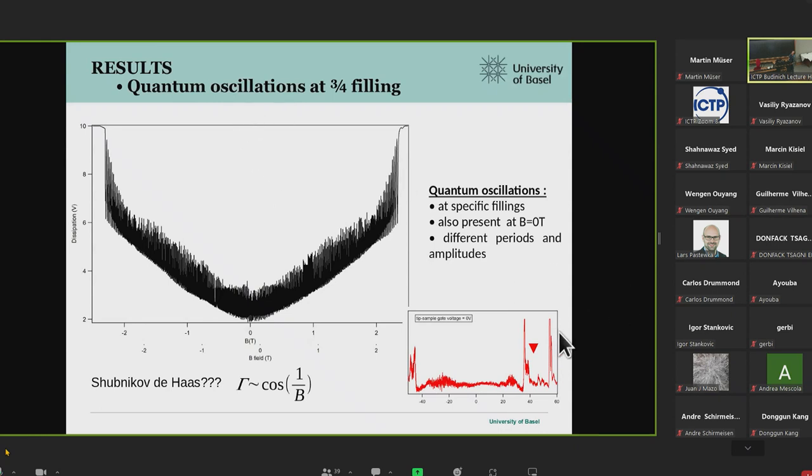Between 3/4 and full filling, we observe something that we called oscillations. So you see dissipation versus magnetic field starts to oscillate, so you have this mustache of oscillations. At the beginning, we were thinking that this could be characteristic Shubnikov-de Haas oscillations, but there are two problems with that. Shubnikov-de Haas would require a metallic Fermi surface, and this is in fact an insulating state, so this Fermi surface cannot be metallic, and the periodicity distribution has to have a